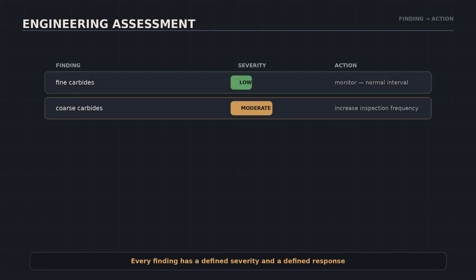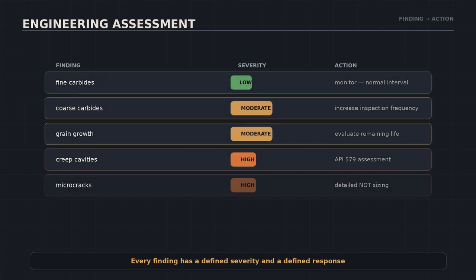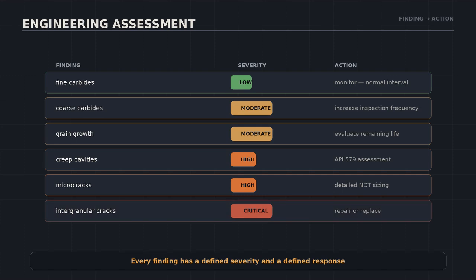So what do you do with each finding? Fine carbides, low severity, monitor on the normal interval. Coarse carbides and grain growth, moderate, increase the inspection frequency and evaluate remaining life. Creep cavities, high, they trigger an API 579 fitness for service assessment. Microcracks, also high, detailed NDT sizing. And intergranular cracks, critical, repair or replace. Defined findings, defined responses.